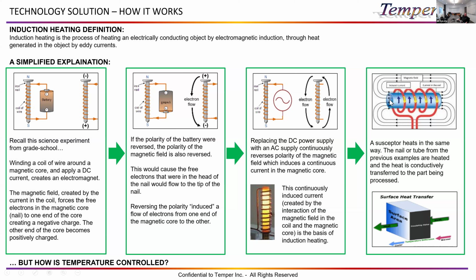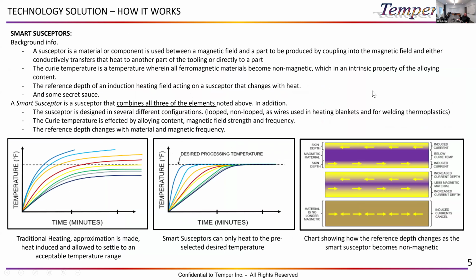Based upon the electron flow, now if I hollow out the nail and make it into a shell, I now have a magnetic field that induces a current into the shell, and then that generates heat, and then the heat is transferred to the part. What makes a susceptor, or that material that the magnetic field couples into, a smart susceptor is that we make the Curie temperature of the material, or that temperature where all ferromagnetic materials become non-magnetic, the temperature that we want it to become non-magnetic at, or where we want it to stop heating.